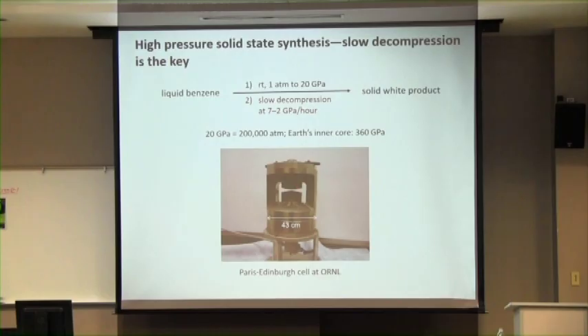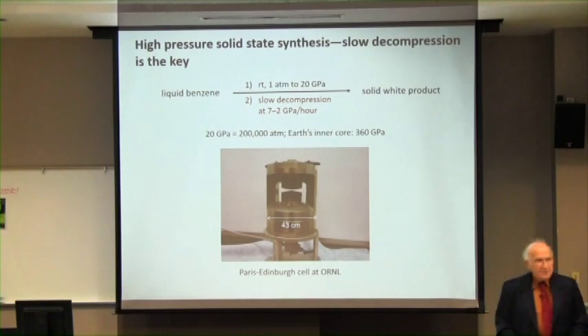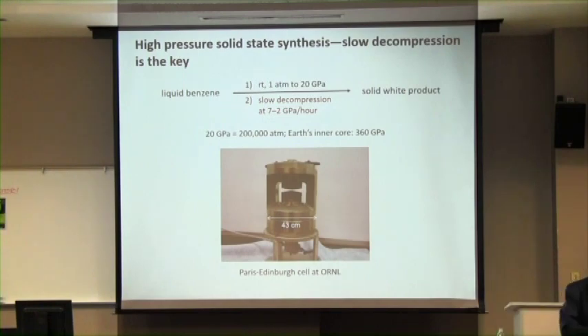It's done by squeezing between diamonds, either single crystals or polycrystalline in this case. This is a special kind of press. As you see, it's about half a meter across or so. There are two diamonds. The squeezing is actually done between the diamonds. The general principle is the elephant's foot principle: there's a force per unit area. The smaller you make the area, the higher the pressure that you get. And this is called a Paris-Edinburgh press.